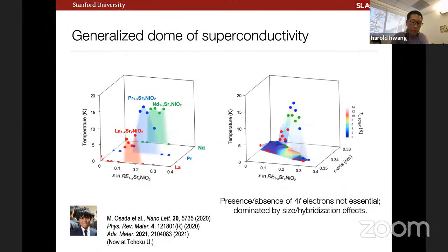Okay. So we and others looked around at other related systems. In particular, we had done an extensive series looking at the original neodymium versus praseodymium and lanthanum. These are the three kinds of systems that we can stabilize, and in all cases we see a dome of superconductivity. And I forgot to mention that the same kind of epitaxial stabilization that's helping us make single crystal thin films is also straining the thin film itself. And so one can project all the variations effectively just to variations in the c-axis lattice parameter. And we see a kind of generic dome of superconductivity here.